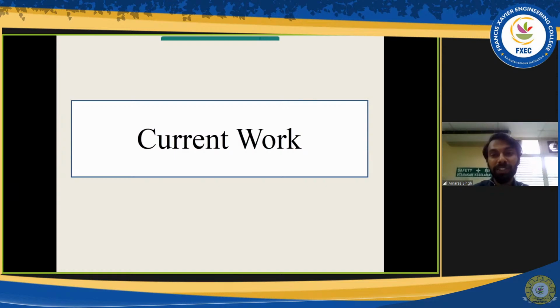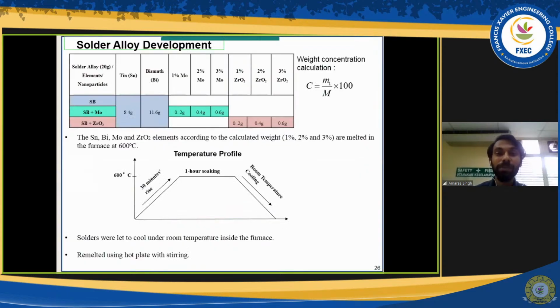I've given graphs and so on, so no worries, it's just a sharing session. This is basically what I've done. I've tried to add in molybdenum and zirconia. MO is molybdenum, ZrO2 is zirconia nanoparticles, and SB is SnBi. As I mentioned earlier, it's a low temperature solder alloy. Why did I choose a low temperature solder alloy? Of course, I don't want a higher temperature than SnPb, which is 183. There might be an argument from the industry that you are using a solder that is still at a higher temperature than SnPb. So I've chosen SnBi.